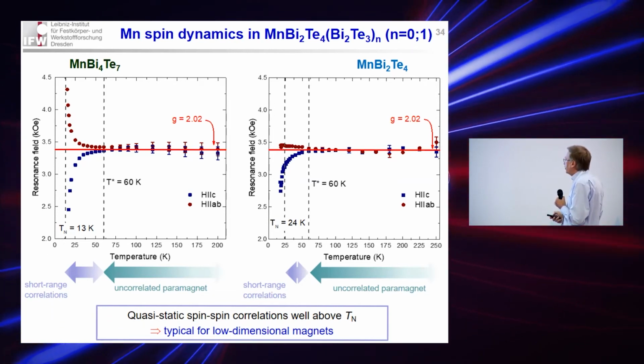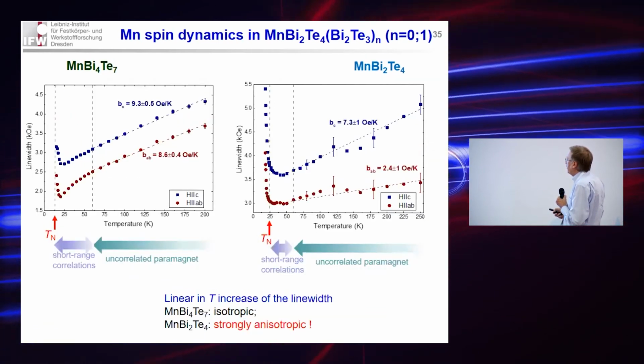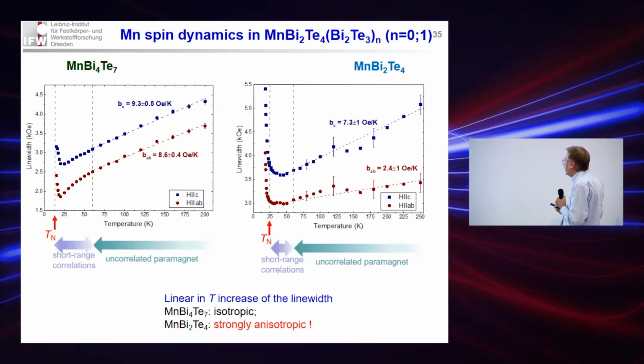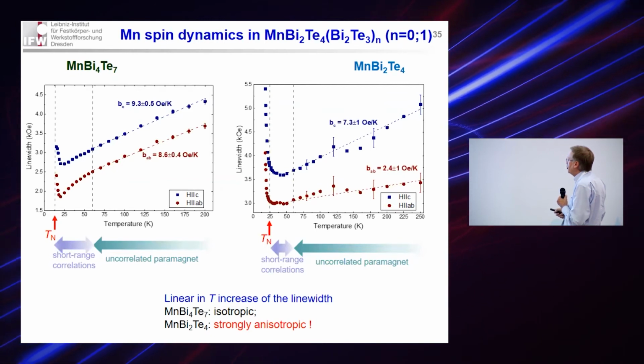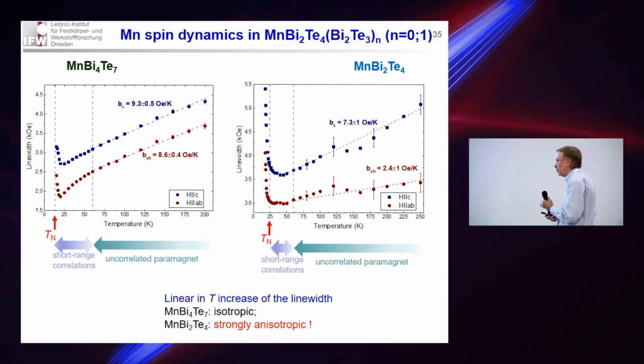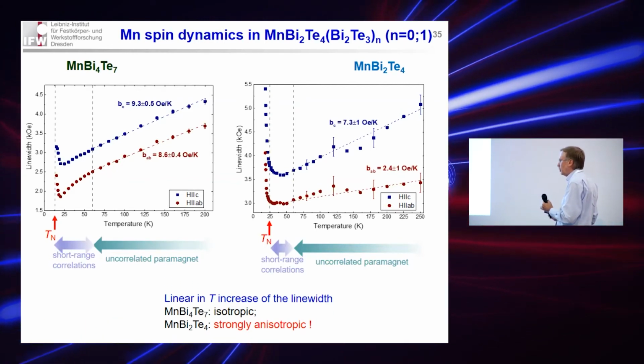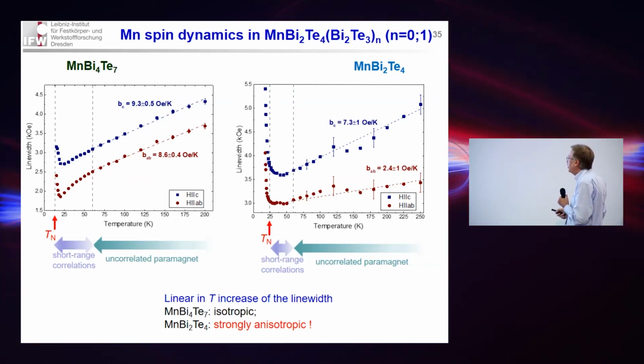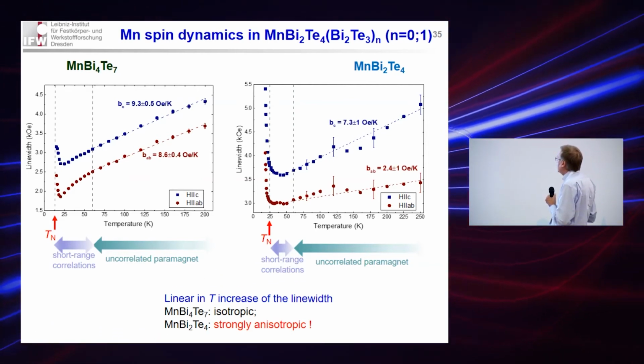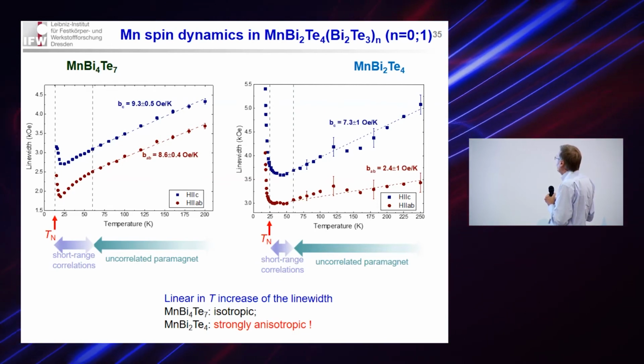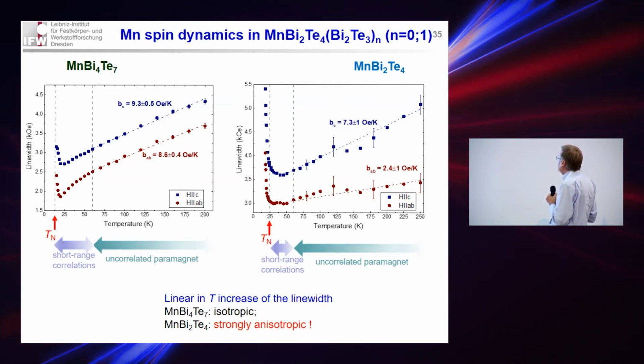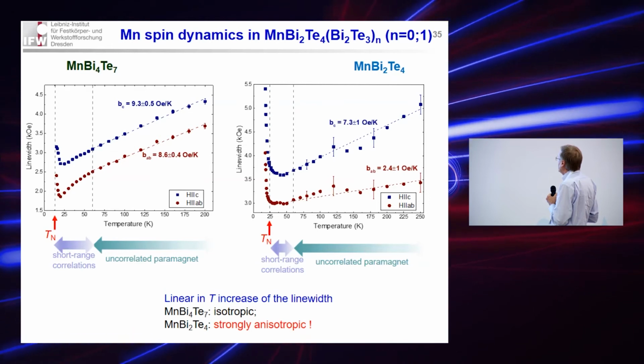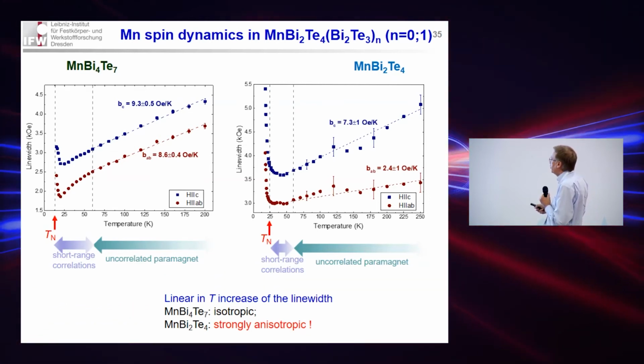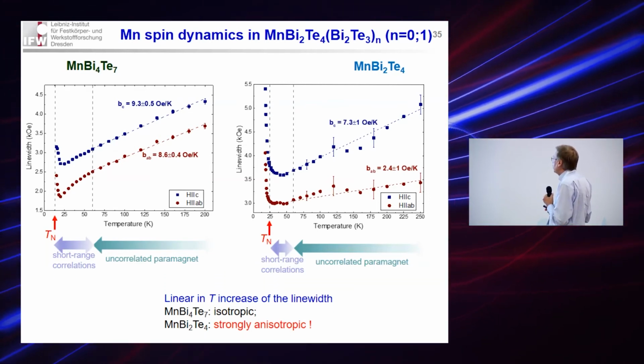Now, if we enter the paramagnetic regime and look at the temperature dependence of the line width, which is the measure of the spin fluctuation, of the spin relaxation of manganese spins, we see a linear behavior in both cases. But in the case of 1 2 4, a more concentrated magnet, the slope of this linear dependence is very anisotropic, and here it's very isotropic. This is also quite unusual.